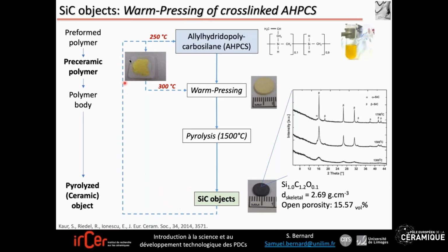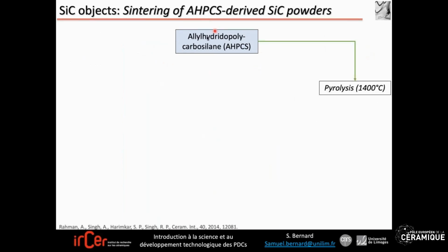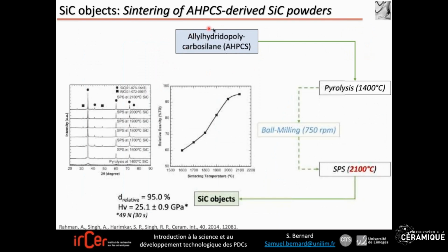But here you need to infiltrate several times your object with the preformed polymer to improve and increase the density of your materials. So this is a time-consuming process. Alternatively, you can use again the preformed polymer, a direct pyrolysis into silicon carbide powders, amorphous, then sintering by SPS here at 2100 degrees C to form your silicon carbide object with such properties, a hardness which is relatively high, more than 25 GPa.